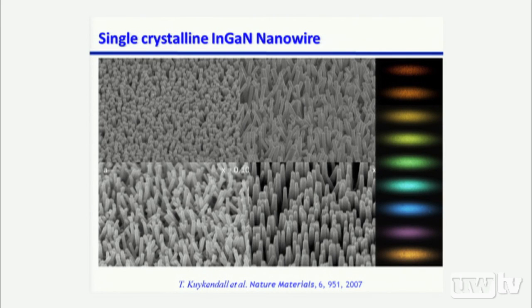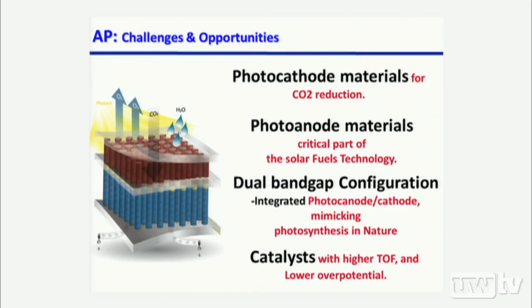Another new composition, which again does not exist in bulk form, only in these high surface area electrodes, is indium gallium nitride structures with tunable bandgap. Both materials we're exploring as suitable photoelectrode materials. And with that, I want to put up this slide showing the remaining challenges in solving the artificial photosynthesis problem.